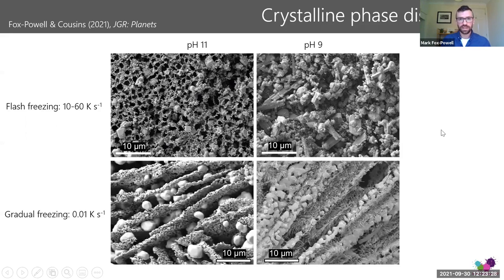frozen fluids represented. And for comparison, in the lower panel are some control experiments where we froze the system very, very gradually at around 0.01 Kelvin per second. So what you'll notice in the upper panel on this scale is small crystals that are homogeneously distributed at this 10 micron scale. And that's in marked contrast to the gradual freezing control experiments where we have these repetitive linear structures forming that are very heterogeneous at this 10 micron scale.